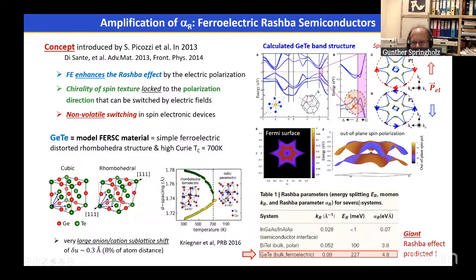From these calculations, they can calculate the Rashba coupling constant alpha, which is basically a ratio between the Rashba energy, indicated here by this red line, and the in-plane separation, E_R and k_R. They derive a Rashba coupling constant of 4.8 eV angstrom, which is really a giant value, much higher than for normal semiconductors. Indium gallium arsenide, for instance, has a Rashba coupling constant that is about 100 times smaller.